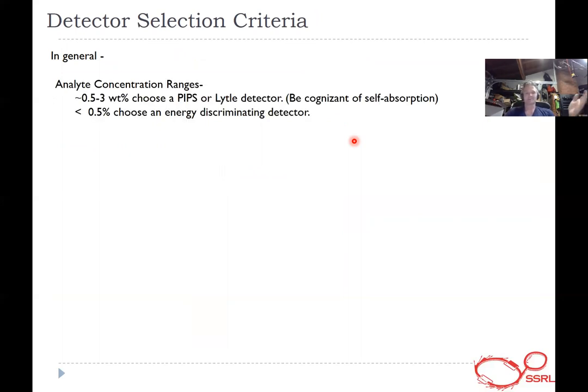So the detector selection criteria. How do you decide what detector you want? In general, as a broad rule, your initial consideration is the analyte concentration range. What is your element of interest? How concentrated are you? For a half weight percent to 3 weight percent, you choose a PIPS or a Lytle detector, but you have to be aware of self-absorption, because as you get high up in that regime, self-absorption may or may not become a problem.